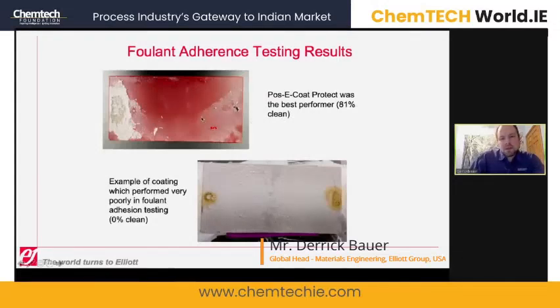So shown up top is a coating that worked, which we call Pos-E-Coat Protect, which did remove most of the ammonium chloride that deposited on the sample. Really, the air blast was focused on the middle of the sample, so that is the only reason why it did not get the deposit that is shown at the edge. An example of a coating that did not perform, which is actually a coating that is used commonly in the industry, is shown on the bottom, where really none of the surface of the coated panel was clean, showing that the ammonium chloride deposits do build up on the surface. Even though this type of coating will release hydrocarbon fouling, it is not effective for releasing ammonium chloride deposits.